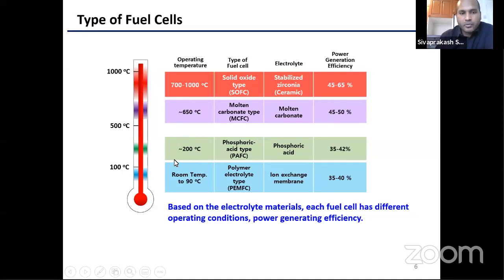Phosphoric acid fuel cells work at 200 degrees Celsius, and the electrolyte material is phosphoric acid. Power generation efficiency is 35 to 42%.